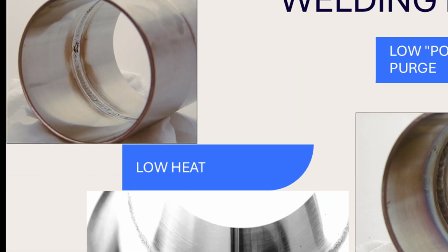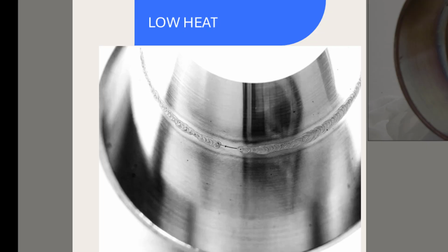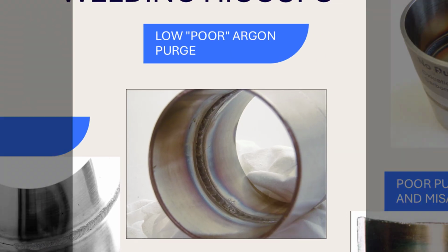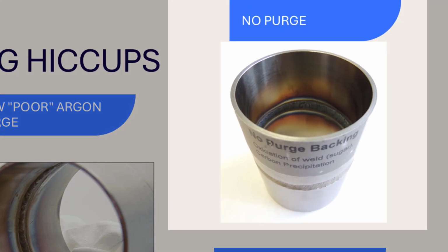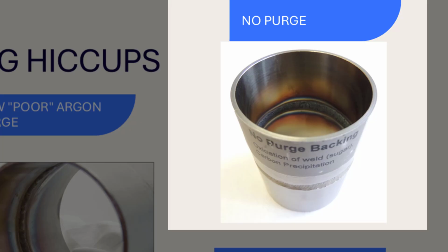Right here you could see low heat. The guy was probably cruising along, thought he had a great weld going, got too comfortable and started to speed up, which causes misses like this to happen. Low "poor" argon purge. You could see this one and this one have some similar characteristics here. If you have low or poor argon, like it's not quite covering it or you couldn't quite get your purging apparatus close enough to it, you're going to probably get this result. And that's not far off from the no purge result. No purge results, that whole entire weldment would need to be cut out.